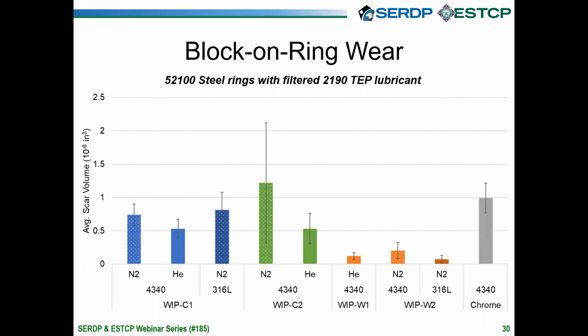And in particular, the WIP W1 coatings had much better wear resistance than the chrome plating. So this is something that we saw with most wear testing we did. There were some cold spray coatings that were worse than chrome, but a large number overall of the cold spray coatings had better wear resistance than chrome in different loading situations.